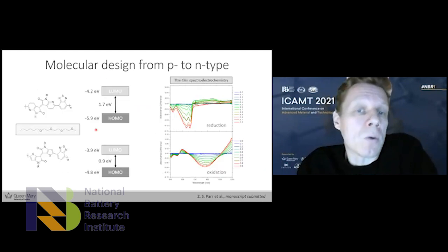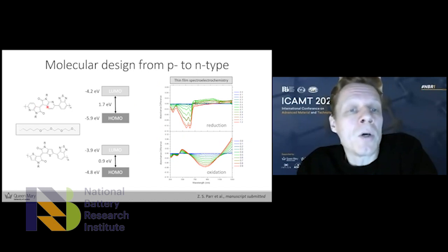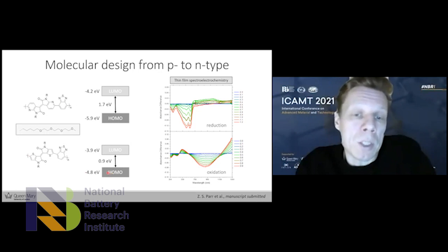The energy levels are quite different for these two materials. The aza isoindigo with the benzothiadiazole has a very low-lying LUMO level, which is good for electron injection into the material, meaning that it's potentially a good N-type material, so transport of electrons. And the thieno isoindigo derivative has a very high-lying HOMO, making a good candidate for P-type charge transport, so injection of positive charges into the material.